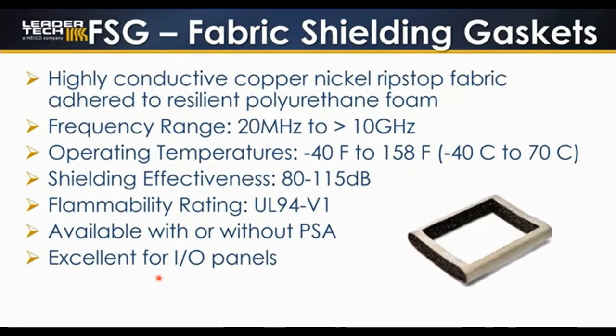We have many standard sizes and shapes available for our FSG, but they are easily customized as well. We can make new sizes to the standard shapes we offer and can also accommodate custom shapes to fit your application. This material can be die cut and laser cut, which you'll see here, and is great for custom I/O panels. We recommend them for frequency ranges from 20 megahertz to 10 gigahertz, operating temperatures from -40 Fahrenheit to 158 Fahrenheit, and shielding effectiveness measured from 80 decibels to 115 decibels. The material has passed a flammability rating of UL 94-V1 and is available with or without conductive or non-conductive PSAs.